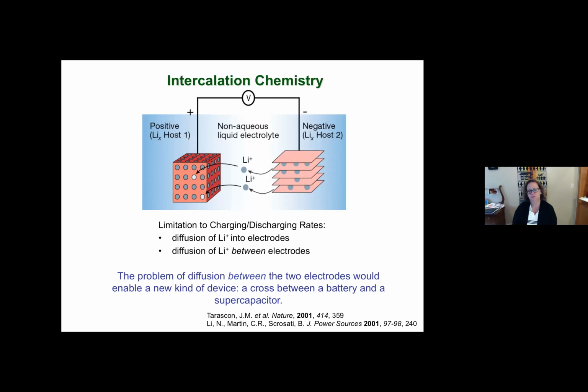So if you could combine really high surface area electrodes, but also make the anodes and the cathodes really close to each other to reduce that diffusion length, it would be possible to build a device that would be a cross between a battery and a supercapacitor. So ideally something that has a very high energy density, but also can charge and discharge very quickly and have a very high power density. So that really is the goal of what my group and I are trying to do and what my company is trying to commercialize. And that requires really thinking about a new architecture for a battery.